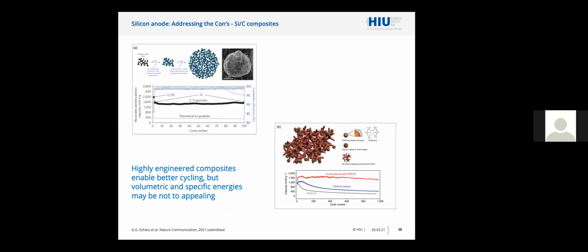There are also more fancy, I call them fancy, highly engineered composites in which very tiny nanoparticles of silicon are deposited on or within three-dimensional structures. These are amazing materials. Good cycle performance has been demonstrated, but do not forget that whenever you introduce an additional component, especially with these three-dimensional electrodes, the overall performance at the end might be lower than even conventional graphite electrode. So never forget what is the real reference material, which is graphite.